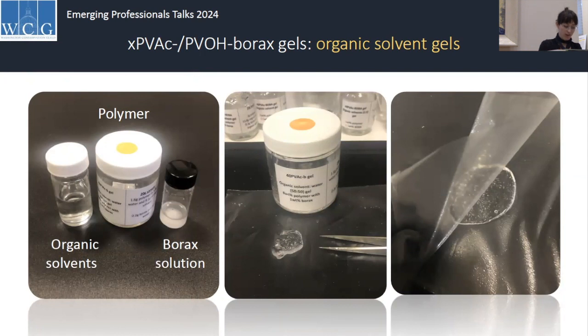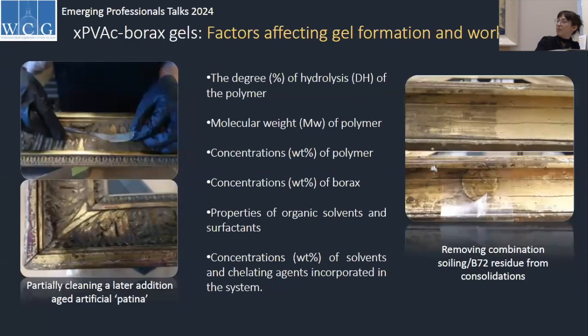Producing viable gels, depending on formulation parameters, is contingent on several factors. Next slide, please. So the degree of the hydrolysis of the polymer, the molecular weight of the polymer, concentrations of the polymer, concentrations of the borax, properties of organic solvents in the system, and the concentrations of the solvent and the chelating agents all have a massive impact on the physical properties of these systems.